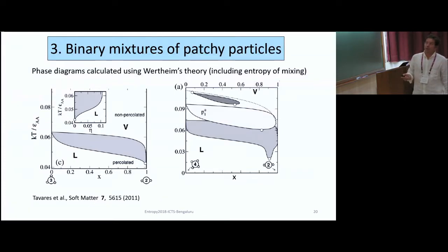On the other hand, when you go to this type of mixtures, we also calculate for 2.5 and 2.6. So these are lower and lower pressures. Let's concentrate on the lowest pressure, which is this one. And this is not similar to this because you have a kind of bulge here. So this bulge means that when you start to increase the concentration of particles of 2 and start to elongate your chains, at some point you have a coexistence between two network liquids.